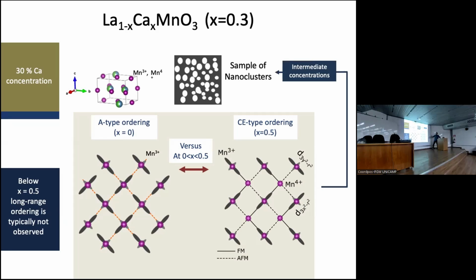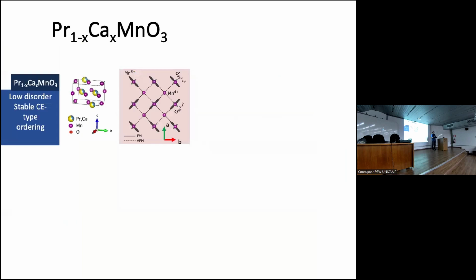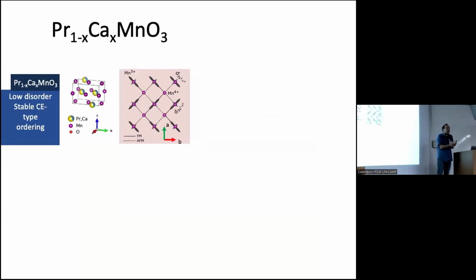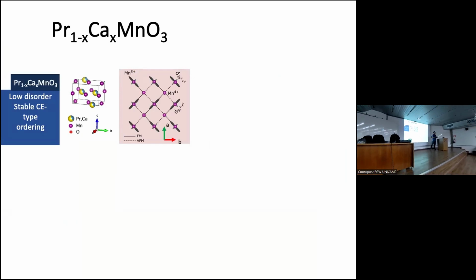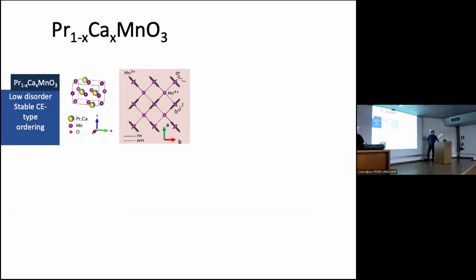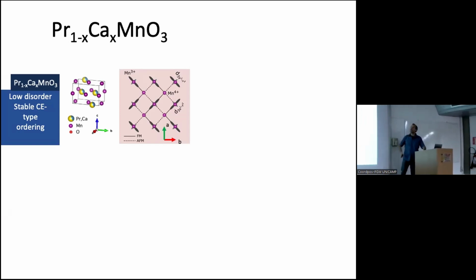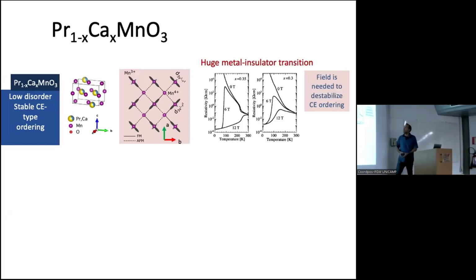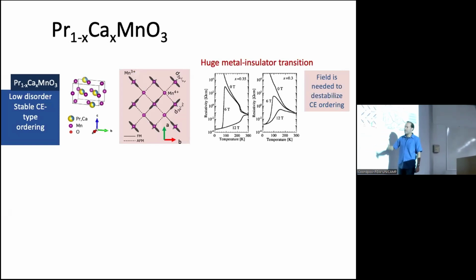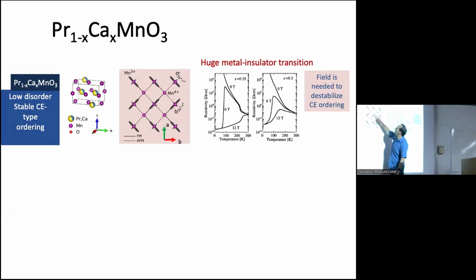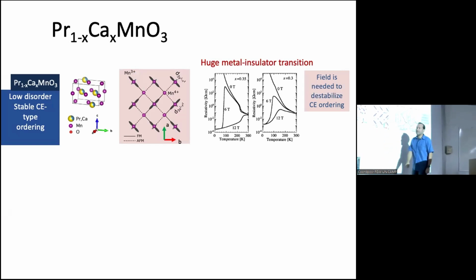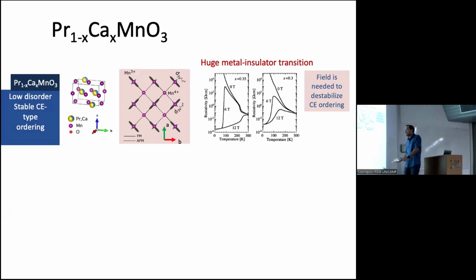It basically breaks down, as you can see here, into small domains. So the sample naturally will organize in a way that there are regions where locally there is ferromagnetic metal, and then the matrix is an antiferromagnetic insulator. So now by adding praseodymium, something very spectacular happens. Basically you have your doping in here, and then you may have a situation where you can have again a mixture between ferromagnetic and antiferromagnetic coupling, but you can break the antiferromagnetic coupling